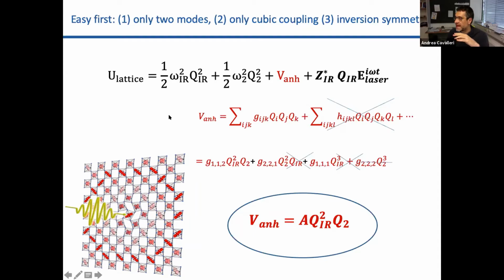And therefore, this will thin down all these anharmonic terms all the way down to a single term here, which is proportional to the square of the driven infrared mode, the one that I'm driving with a light field, times some other mode. So this is the lowest order anharmonic coupling term that I can think of if I make these three assumptions. Just to remind you, this is the term that gives you thermal expansion, this Q squared Q coupling, when one studies the basics of condensed matter physics. The lowest order expansion of the anharmonic interactions in a solid are of this type, Q squared and then strain, and gives you thermal expansion. But anyways, under these assumptions, I will consider what the physics is of a material with two modes, with inversion symmetry, and with this type of anharmonic coupling.